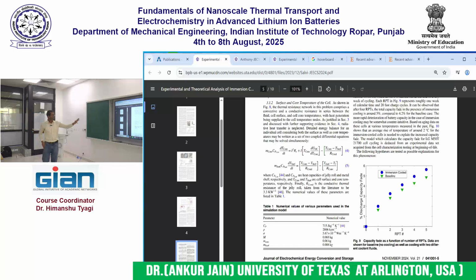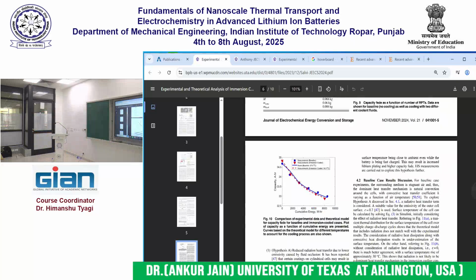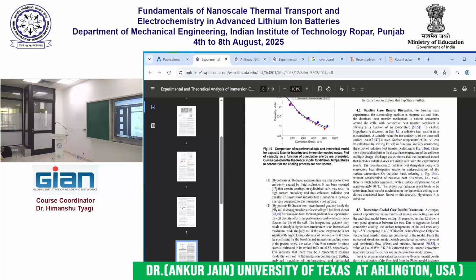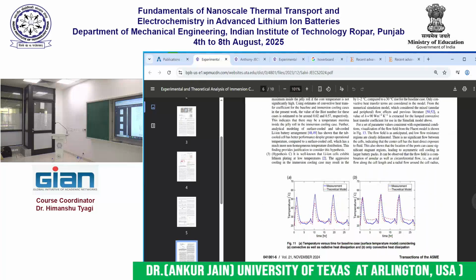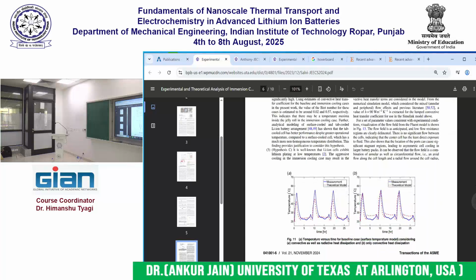So while immersion cooling is good for thermal management, we found that we still need to tune it in order to minimize these. It's not a great effect, it's only maybe 1% additional capacity fade, but nevertheless this needs to be understood fundamentally, and one may need to design the thermal management system to minimize this undesirable effect. So the rest of the paper was simply on running a bunch of experiments to try and understand the mechanisms behind this capacity fade.